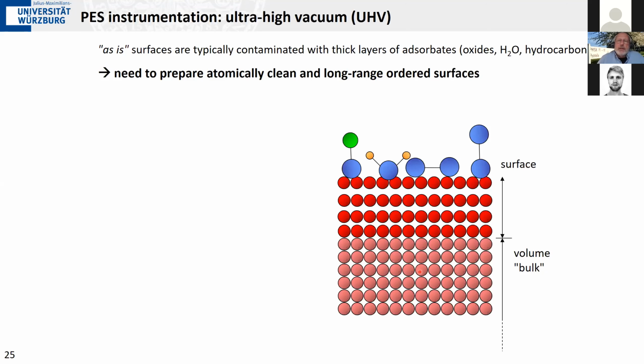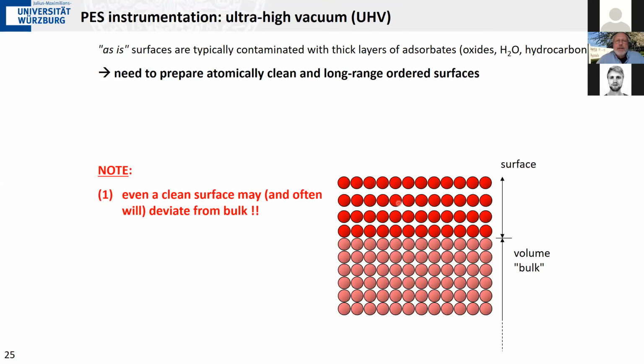Now you have to remove this. Remember that the mean free path of the photoelectrons is just a few angstroms. And if you start out with a surface like this, which is contaminated, and you try to excite photoelectrons, most of your photoelectrons will come from this adsorbent layer and not from your actual sample that you want to study. So what you measure would be the dirt, but not the sample itself. So you have to remove this dirt first. By some means, you can either cleave your crystal, or you can try to clean it by ion bombardment with argon ions and subsequent annealing, or you can just anneal and hope to clean your surface by just thermal treatment, and that's then what you should be looking at. But the lifetime of such a clean surface is not particularly large, especially not if you do this at normal conditions.